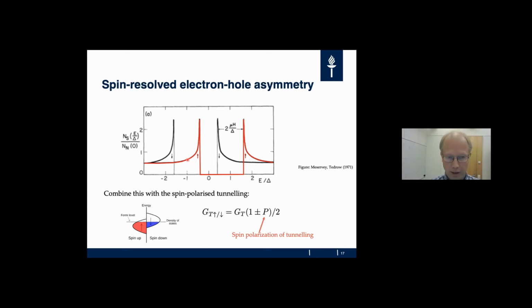Another way than just describing this kind of Zeeman mode, or the spin split mode, of the density of states here is to just look at the spin resolved density of states. So spin up, due to exchange field, spin up density of states shifts to the right, and spin down density of states shifts to the left. But the superconductor actually still knows where the zero is, because this is the chemical potential of the superconductor.